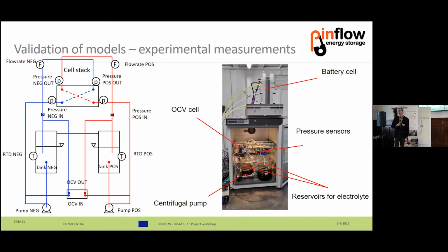Okay, we also validated our data by experimental measurements. Here you can see a scheme of our experimental measurements of pressure losses. For measurement of pressure losses, it was very simple. We just charge the electrolyte to the required state of charge. We temper it. We set the desired flow rate, and we measure the pressure before and after the cell, and from the difference of these two values, we get the pressure difference on the cell.